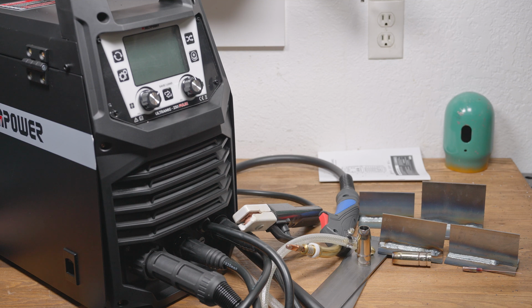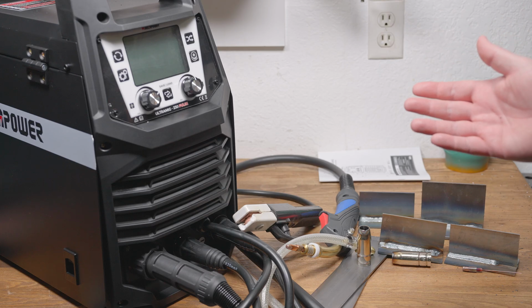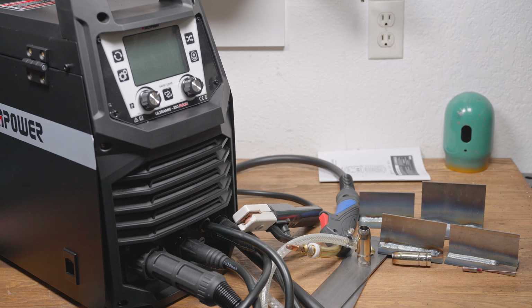And when that inner layer starts to burn, the inner metal sleeve would actually come loose and spin free inside, making it extremely difficult to remove the nozzle from the diffuser. So if you want to push this machine very hard, you'll probably want to invest in a heavier duty MIG gun. Maybe Decapower will include a larger MIG gun in the future. If not, the included one works okay, just not so much for high amperage pulse. We'll see how it holds up when welding aluminum. I haven't yet tested aluminum or flux core. I think that will be in another video.